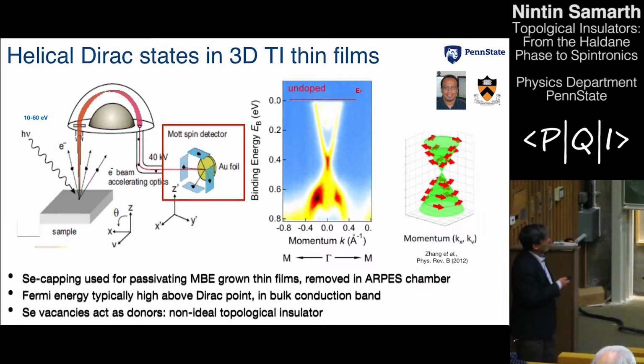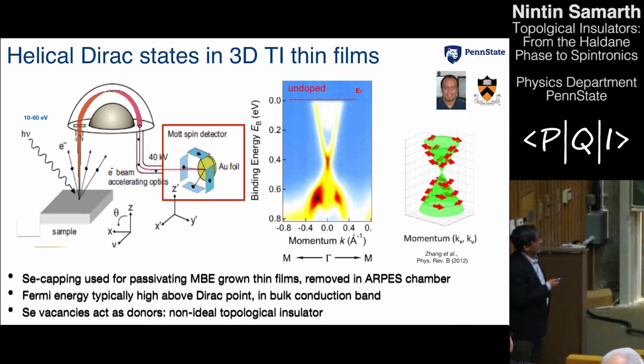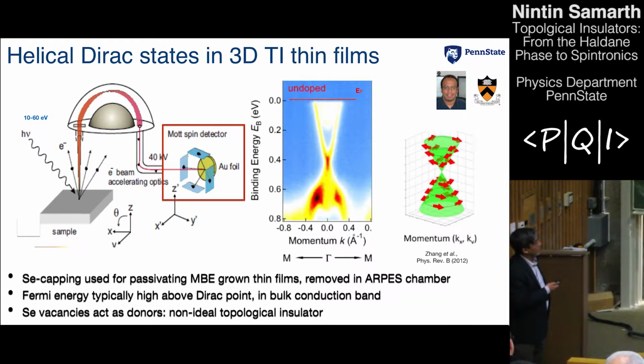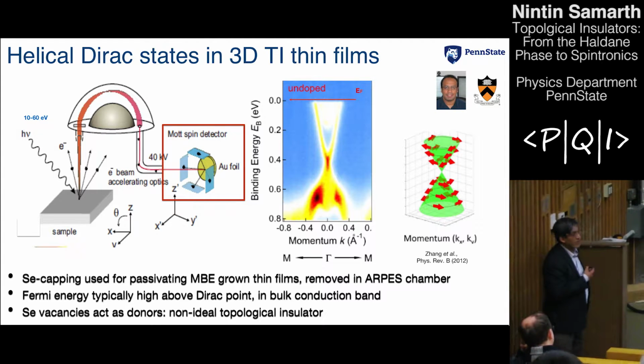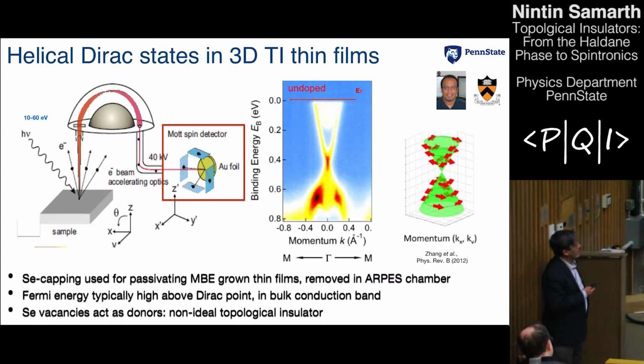Furthermore, by using a gold foil, which serves as a Mott spin detector, they can do a spin-resolved experiment where they map out the spin as a function of energy and momentum in these materials. Okay? So there are a variety of defects in these samples that occur when they are grown by the method we use. And one of the typical defects is called the selenium vacancy. So this is a missing selenium atom in the crystal structure. And what happens is that donates electrons, and because of that, the chemical potential in the samples is typically far up in the conduction band in the as-grown samples. And this leads to some difficulties that I'll explain in a minute.